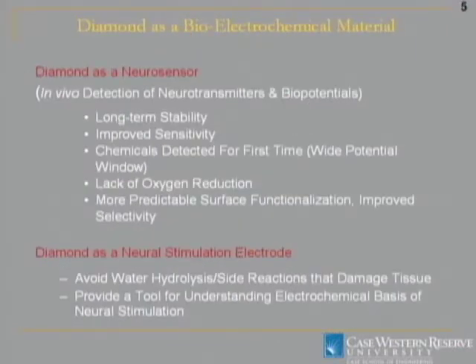So in terms of the advantages of diamond as a bioelectrochemical material, for diamond as a neurosensor, and again we're talking about in vivo detection for both chemical recording and electrical recording, the number one advantage is this idea of long-term stability. There's also, as I'll show you, the potential of improved sensitivity for chemical recording or electrical recording because of what we call the low baseline current of the electrode. The wide potential window, as you'll see, will allow us to maybe look at chemicals that we couldn't detect before. And I already mentioned the lack of oxygen reduction.